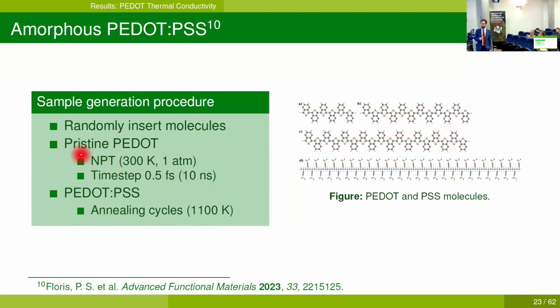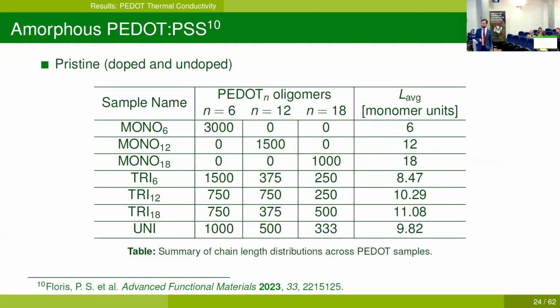So of course, for pristine PEDOT, we have simulated them both in the undoped and in doped state to create a baseline and then to see how doping affects the thermal conductivity. So this is a summary of the samples that were created. And you can see here the various chain length distributions. So for example, the first line refers to samples that only contain chains of 6 monomers. The second line only contains chains of 12 monomers, and so on. And here, the average chain length is summarized. So we have 6, 12, and 18 in these 3 cases, and somewhere in between 6 and 12 monomer units of average chain length for the other samples.